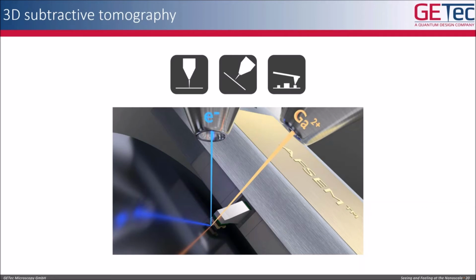In this case, we integrated the AFSEM system in a dual beam system where you also have the ion beam available, so that you can really use the ion beam, in this case a gallium beam, to modify your sample and look at these modifications with the AFM.